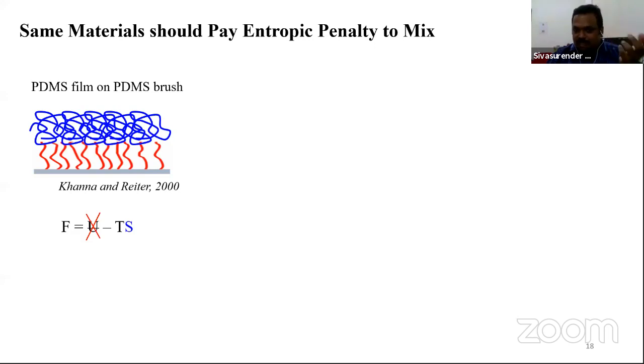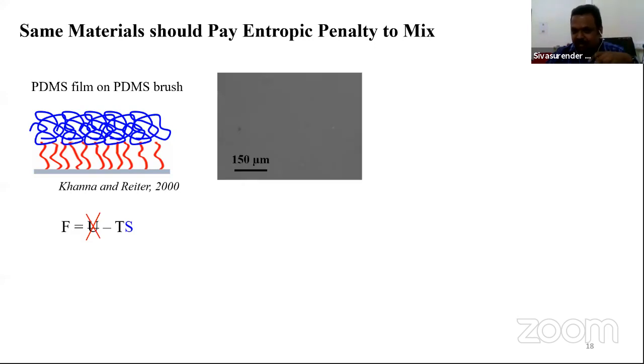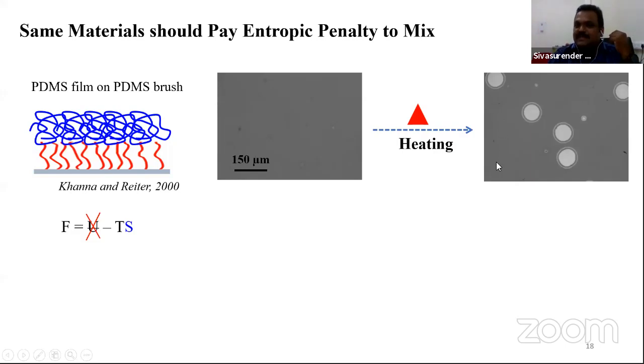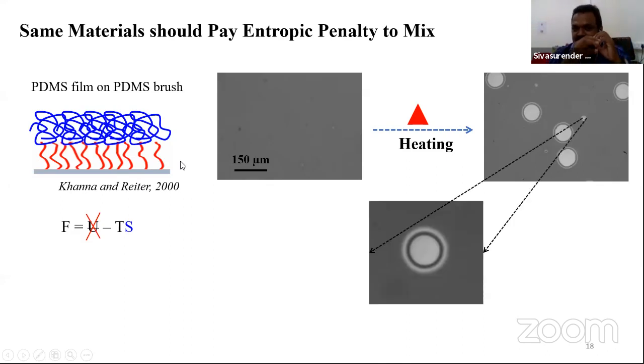And to look at this system, they made a film and put this film under an optical microscope, which also has a hot plate, right? And they can now look at this film while things are happening. At low temperature, everything is frozen, so nothing is happening. And when you give temperature to this system, what they have seen is that this film starts dewetting. I mean, it starts forming holes and retracting from this polymer brush layer, right? So now I'm showing you a snapshot of the movie where a single hole is growing.